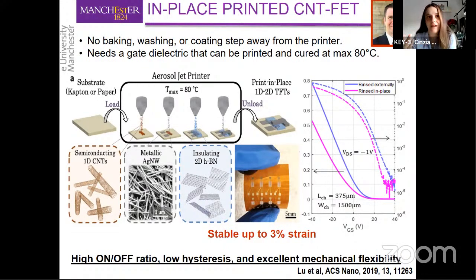So annealing will be done, for example, by increasing the platen temperature, which can go up to 80 degrees maximum. So the fabrication of this device is done under very restricted conditions, under a maximum processing temperature of 80 degrees C. And despite that, the device, if you look at the transfer characteristic, is actually showing very good performance, very good mobility, very high on-off ratio, and very important, very small hysteresis.